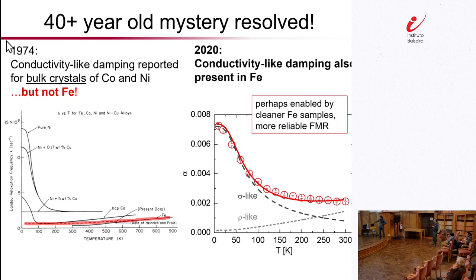I will point out also another interesting thing. You see another alloy here. This is a mixture of nickel with 5 weight percent of copper. Here, the damping stays relatively constant. What I imagine is that the electrical conductivity or resistivity is likely only weakly dependent, mostly constant with temperature as well. Just looking at this is already quite fascinating to me. This already suggests a close relationship between electrical conductivity or resistivity and the magnetic damping in the magnetic metal.